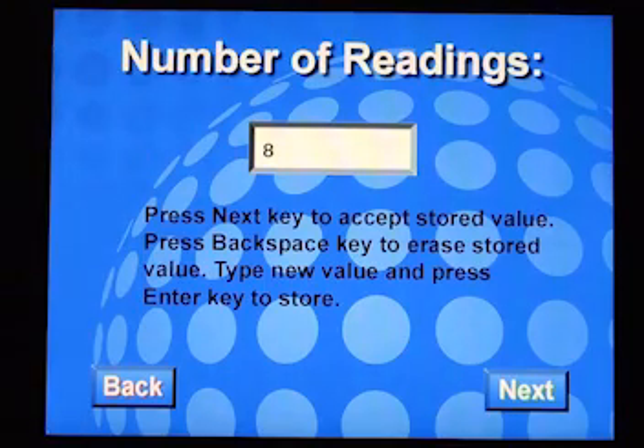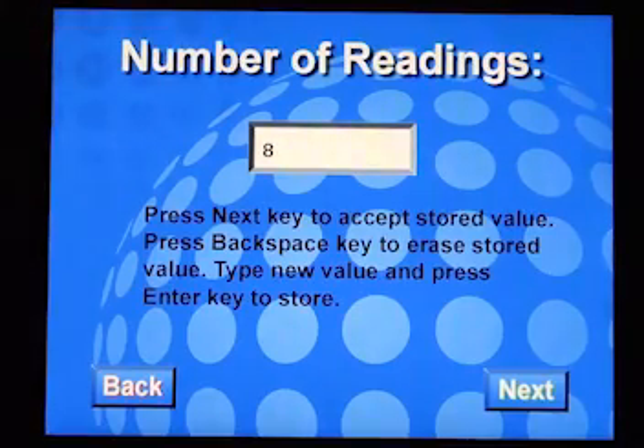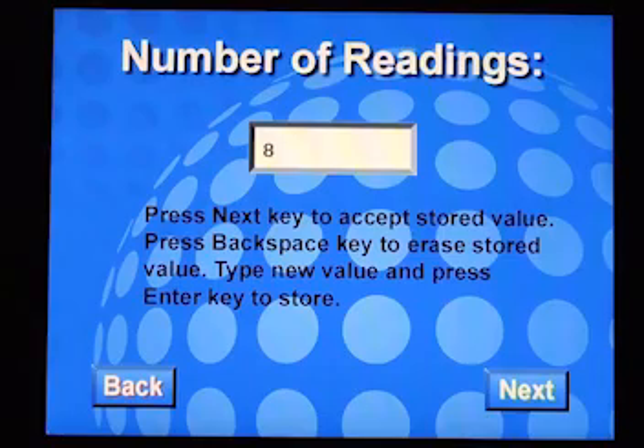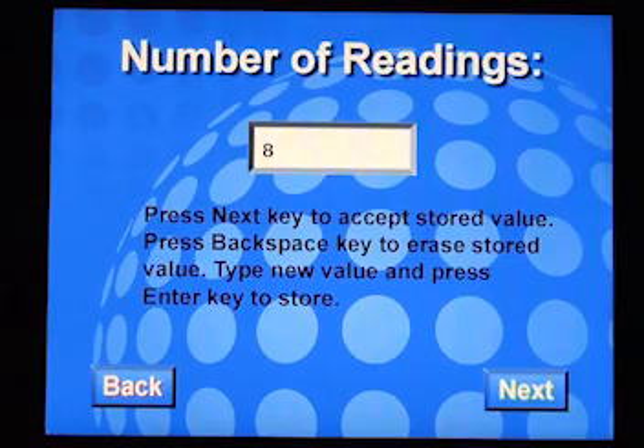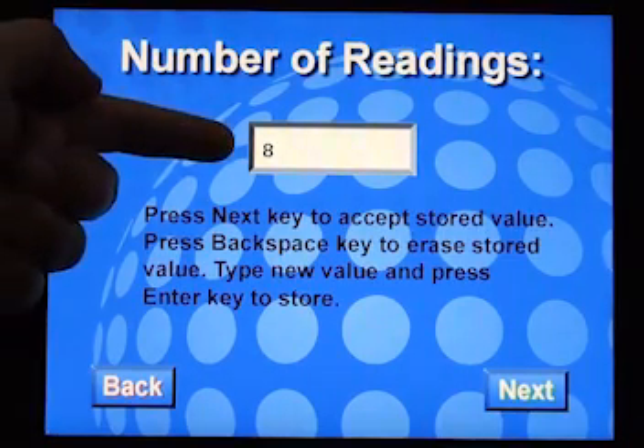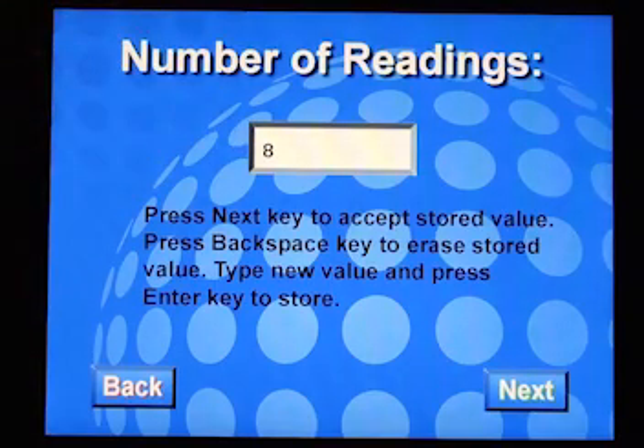Number of readings is the minimum number of sample readings the system will take per sample. In this case, we chose 8, but this number can be any number higher than 2 and lower than 45. This is the number of readings the system will do without using the percent difference criteria. After running this many readings, the system will start comparing the last 2 results to decide when to stop.